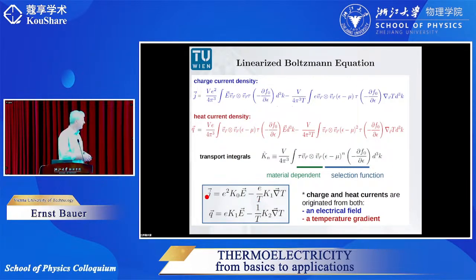And the electric current density is then proportional to the electric field. And the proportionality constant is nothing else than the conductivity. So the electrical conductivity is given by this K0 transport integral. And then you can see 0 means here 0. There is no energy of importance. The only energy dependent term is this derivative of the Fermi-Dirac distribution function.